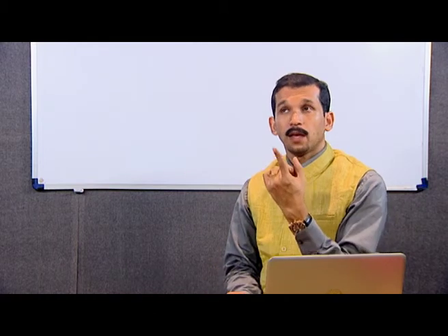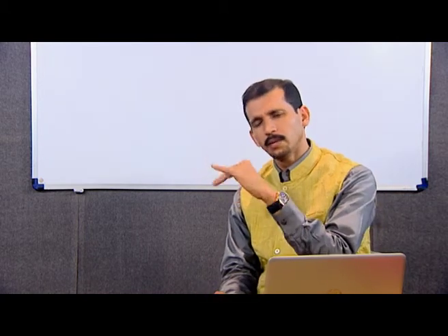And coming to size, crystallites in general should be less than 10 micrometer on an average to get good powder statistics. As shown, a typical XRD spectrum will have three different contributions. First and foremost, the signal. Signal is what we need for a sensible estimation of what the XRD is about, so it is the most important part. Second is the background.